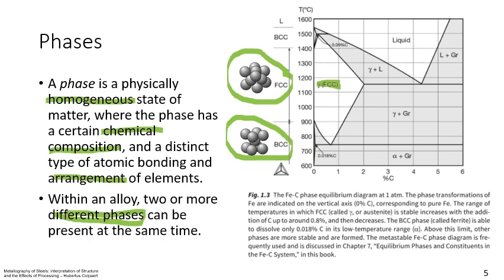But most of our line pipe steels will have carbon in excess of 0.018 or 0.022, depending on which phase diagram is being used. And so they will be two-phase combinations that will be present at the same time.